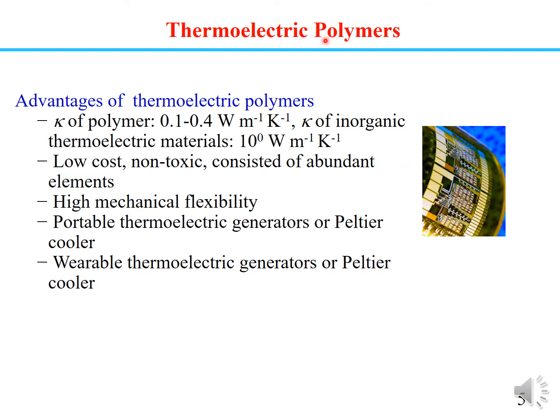Hence, thermoelectric polymers gained great attention because of their unique advantages. Their thermal conductivity is lower than inorganic thermoelectric materials by 1 to 2 orders of magnitude. Polymers can be cheap, and they consist of non-toxic and abundant elements. They can have high flexibility, so that they can be used as portable or even wearable thermoelectric generators or coolers.